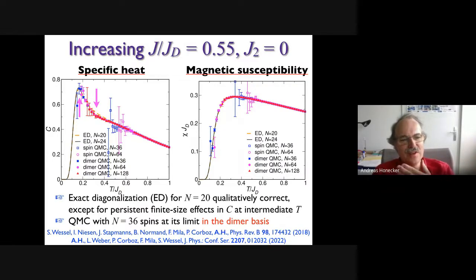it stops looking as nice. So now the dimer basis quantum Monte Carlo doesn't get to the low temperatures any longer either. So this is now the ratio 0.55. But first of all, the single spin basis quantum Monte Carlo breaks down long before you get there. With the dimer basis, you can approximately still resolve the maxima of the thermodynamics.